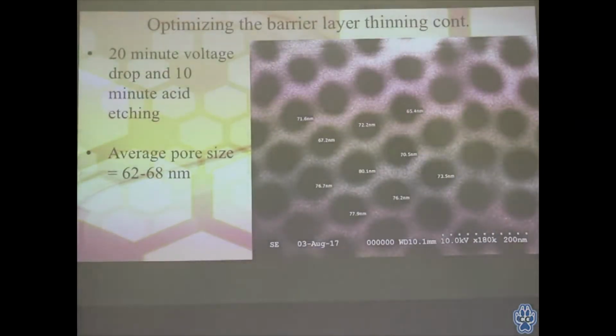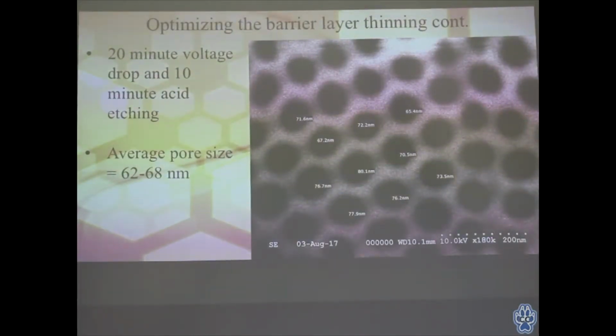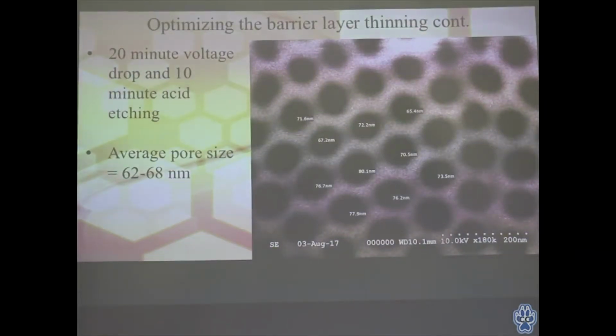So we decided that we were going in the right direction, so we thought, why not increase the voltage drop? So we went from a 10-minute voltage drop to a 20-minute voltage drop while still keeping that 10-minute acid etching. And again, the pore sizes did increase as well without losing order again. So we were able to go up to about a 62 to 68 nanometer average, which we were really happy with considering we started around 40 to 45.